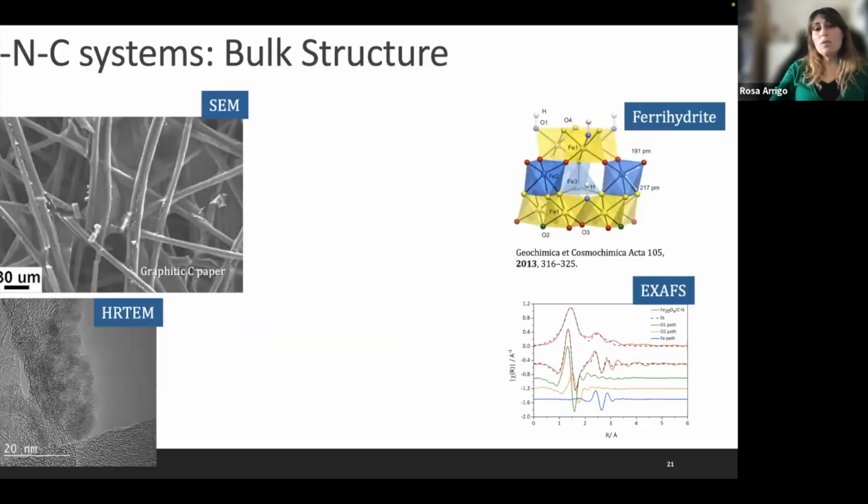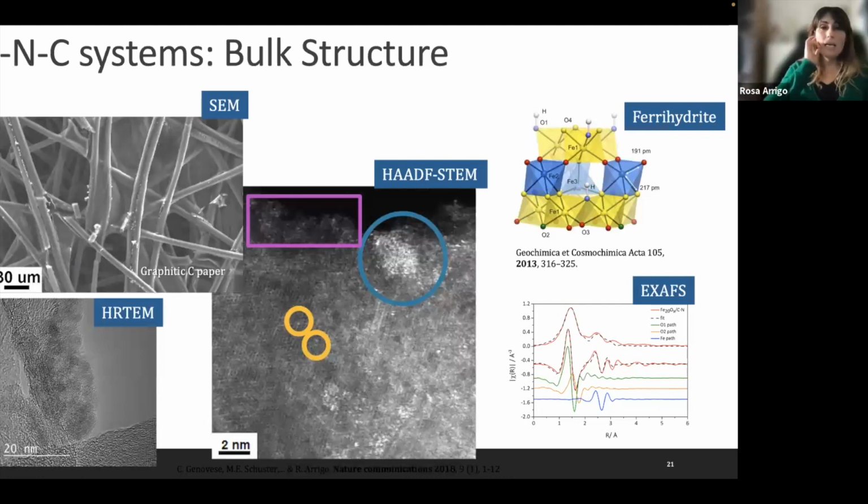Now, what I'm going to show you is an example which we have been looking at, this iron, nitrogen, and carbon system, where the carbon was a carbon support, like carbon nanotubes or activated carbon. And we always found that in the CO2 electroreduction in both gas phase or liquid phase, the nitrogen functionalization at 873 K, or high temperature, basically in which we stabilize all the nitrogen species I showed you before, has a beneficial effect, and particularly we see carbon-carbon coupling chemistry.